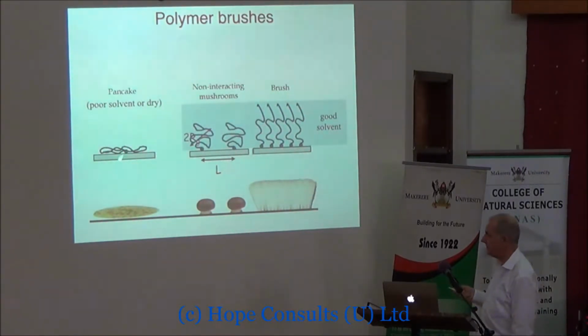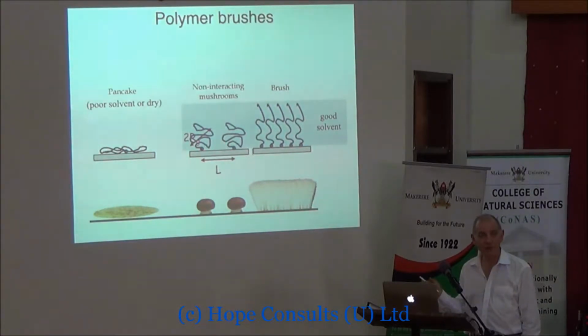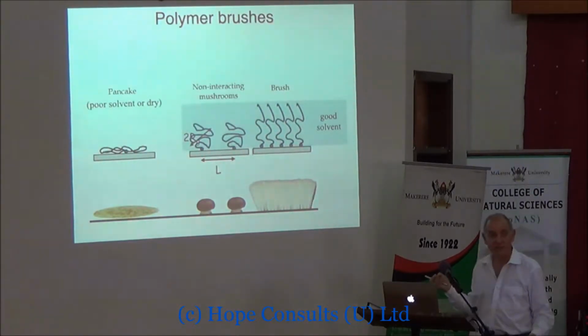If it's dry or if it's in a bad solvent, it will collapse. But if it's in a good solvent for this polymer, and the polymer chains are spaced fairly widely, then they adopt the same shape they would have if they were floating around in solution, except one end's attached to the surface. And we call that the mushroom configuration.